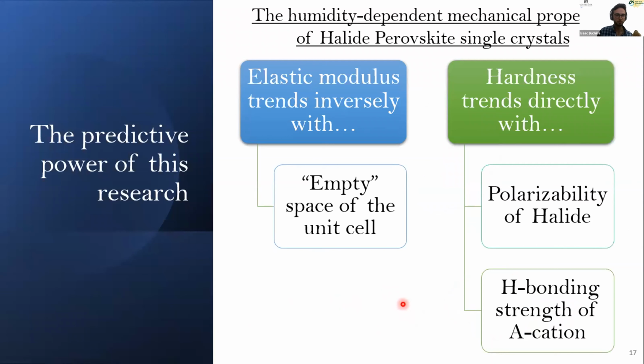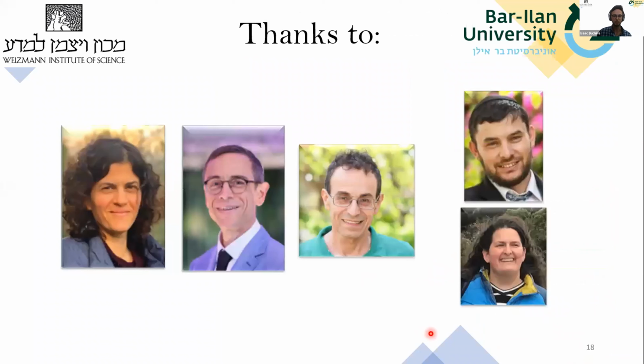Overall, this research shows that the elastic modulus trends inversely with the empty space of the unit cell, and the hardness trends directly, but weakly, with the polarizability of the halide chosen for the crystal, and strongly with the hydrogen bonding strength of the A-site cation. Are there any questions at this time? And if we have time, I'd love to take some.